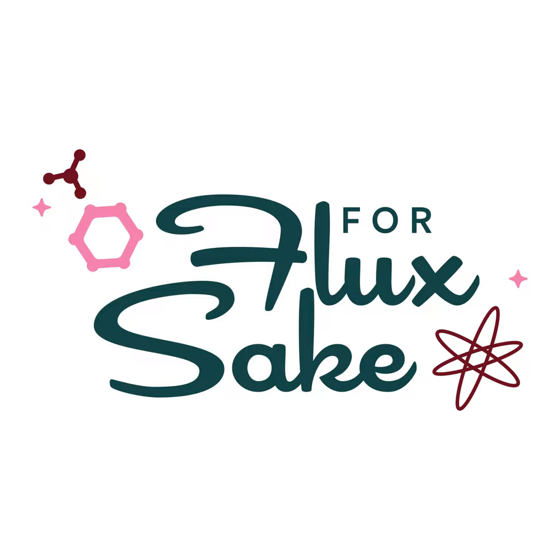So there's certainly that. The next thing that people freak out about is, is it sanitary for crazing? Because they are literally rifts that go into the clay body. And the answer is, if the clay body is vitrified, it's perfectly fine. Now, if it's not vitrified, you definitely can get water that'll penetrate the crazes and then get into the clay and grow mold. That absolutely does happen. Or I've seen it too, where water has gone down into the craze and discolored the clay body. And it's permanent. You can see it sweat under there when the water soaks in. It's really ew. Gross. Yeah, ew is right.